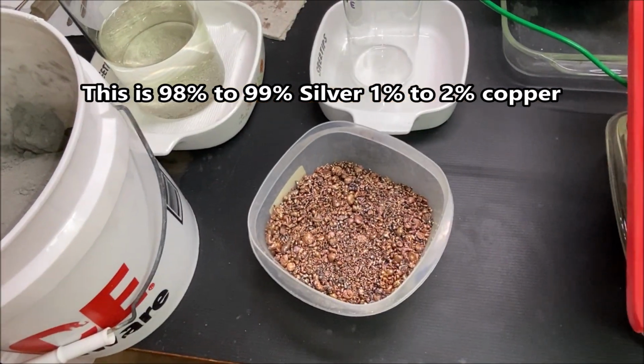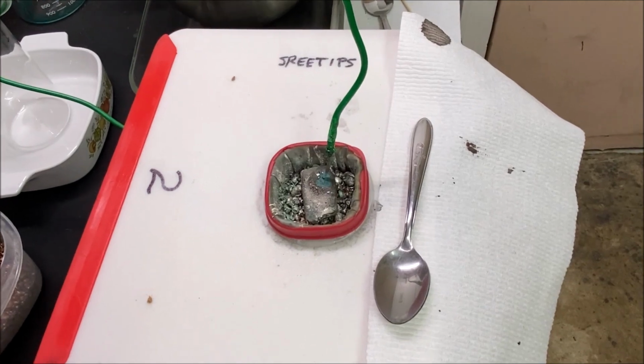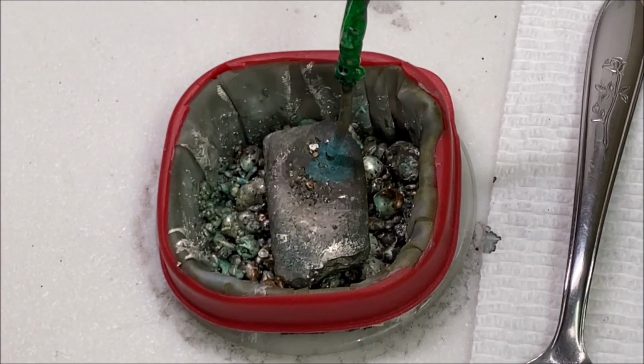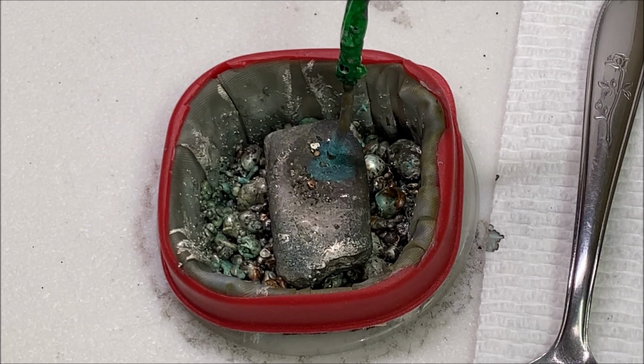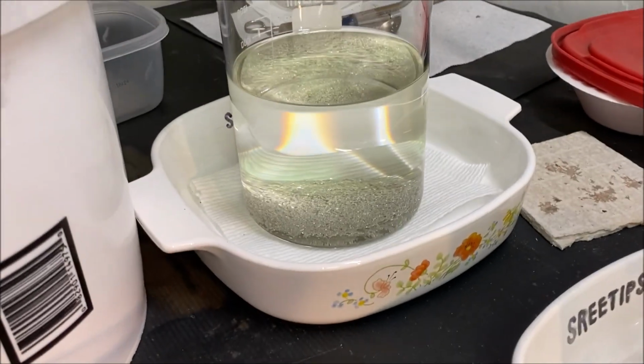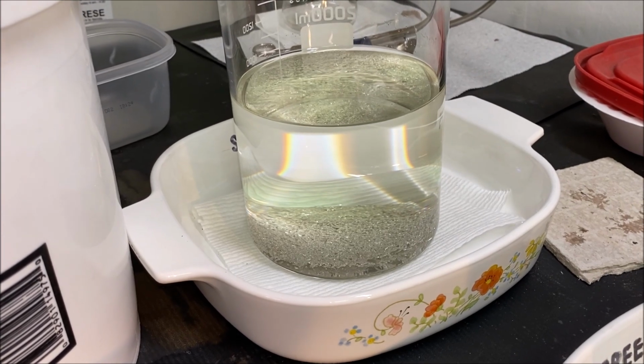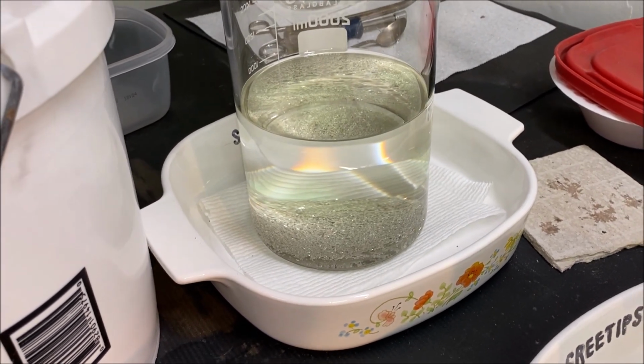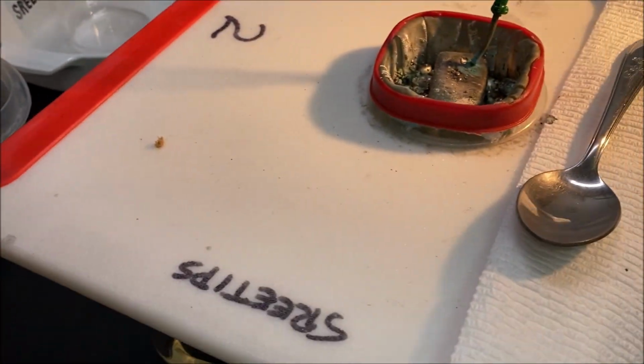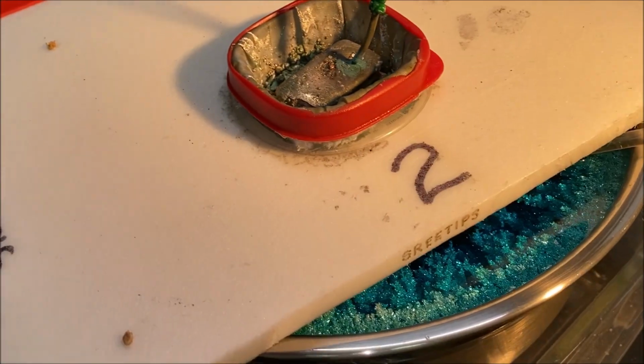And then I run it through the silver cell down here. I add it to that anode filter basket. We pass an electric current through it. The silver dissolves, passes through that Dacron filter, and then it deposits as high purity silver on the inside of the stainless steel bowl that is the cathode. This is our electrolyte that we made earlier in the video. And we'll use this when we do the harvest on silver cell number 2 here.